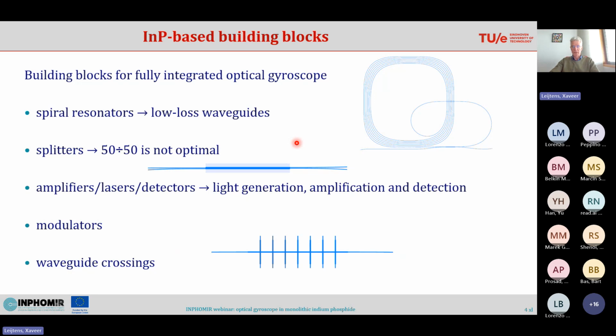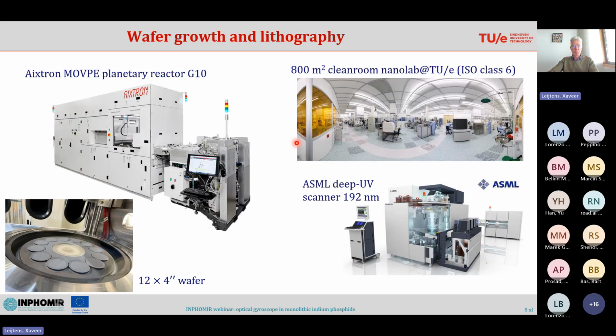I'll go through these things in a bit more detail, but first let me show you how we do the integration of active and passive components. For this, we grow our layer stack in the clean room at TU/e. We have an Aixtron MOVPE reactor, and this reactor can grow twelve 4-inch wafers at the same time. We have different etching machines for the different materials, wet chemical etching as well, and we have an ASML deep UV scanner for the photolithography, mainly of the waveguides.